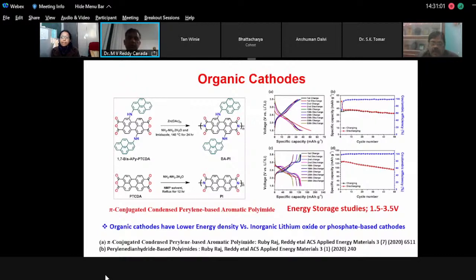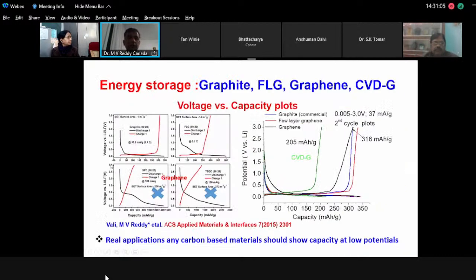So regarding anodes, I think people are talking about graphite being more popular. If you talk about the graphene type, although this material may not be useful because of the higher ICL, I think this may not be promising. So practically, the more interesting material is still graphite. Why? Because we can get a lower discharge charge potential at lower voltage.